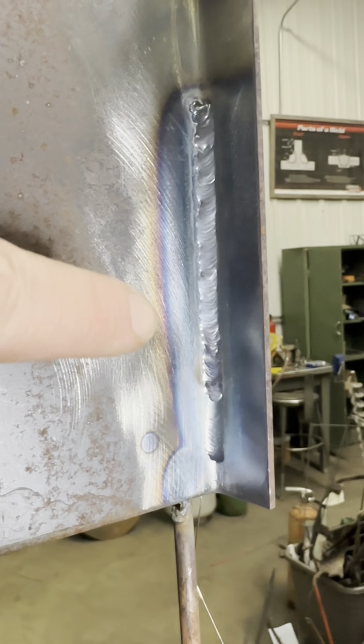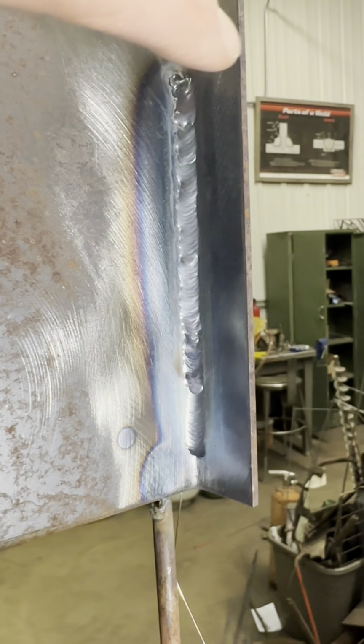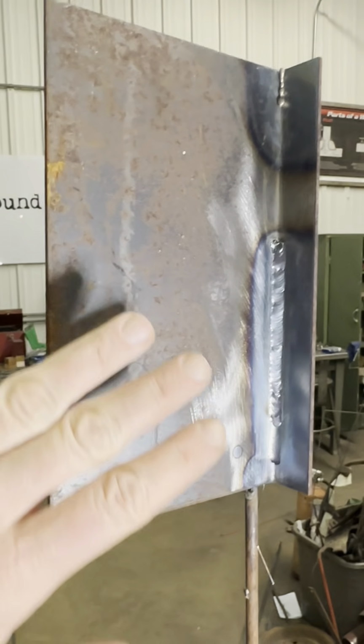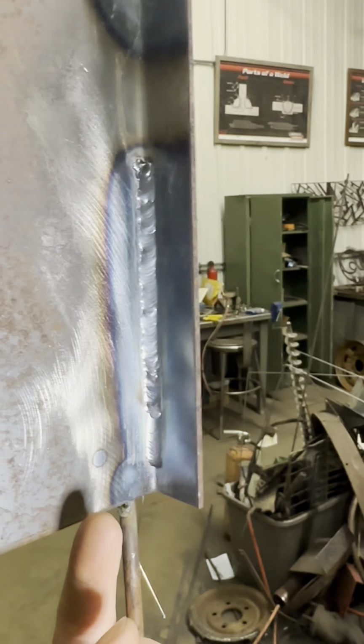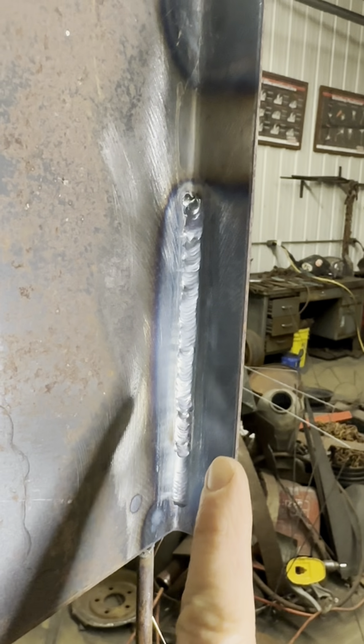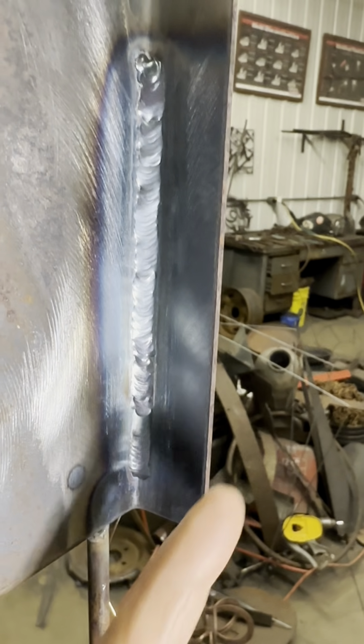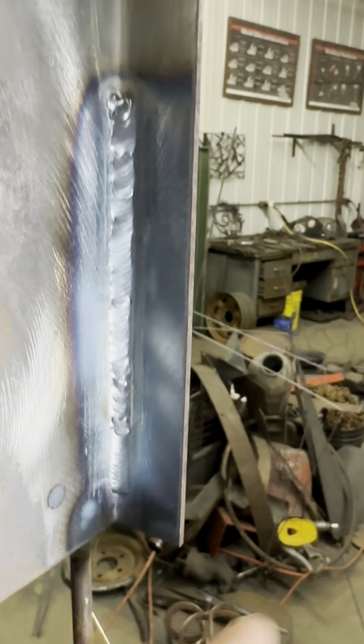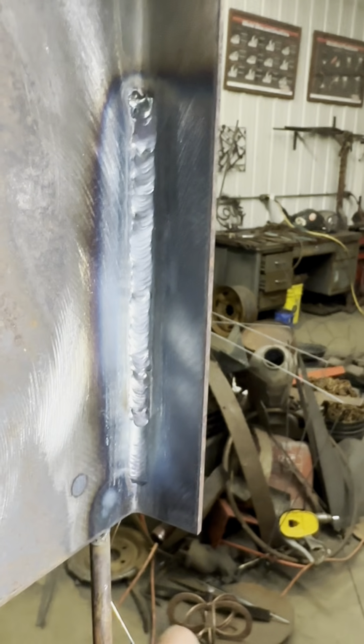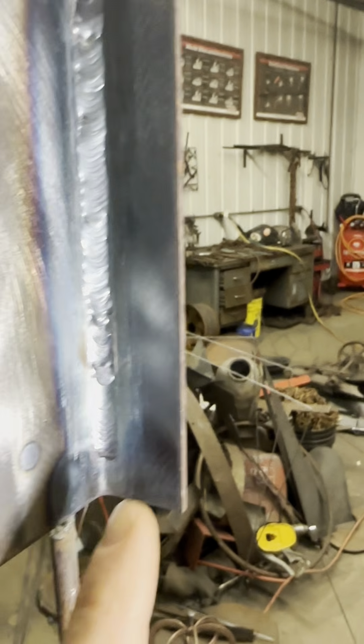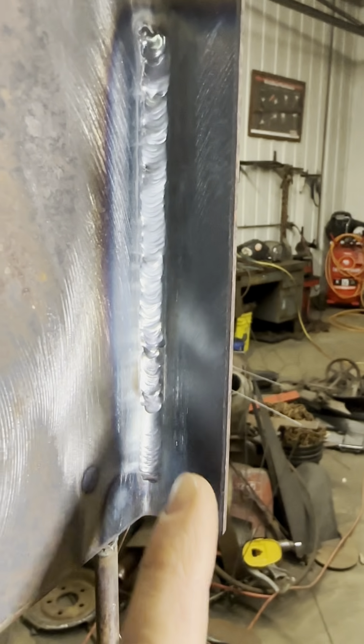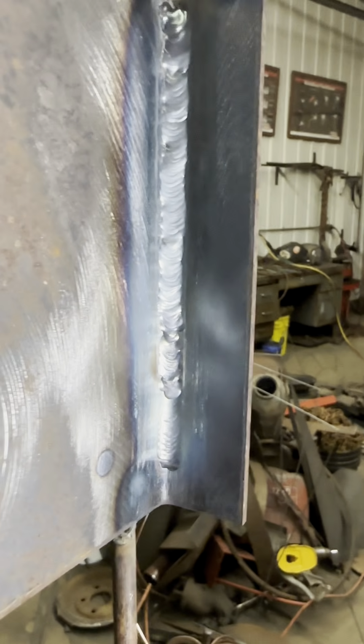By the way, this is a term I don't throw out very often. This is the HAZ, H-A-Z, the heat affected zone of the weld. And as you can see, because there's a lot more material here to act as a heat sink, the HAZ only goes so far out from the weld, but it consumes this entire webbing here that's only like a half inch big. The heat didn't have anywhere to go. It couldn't escape off the plate, so it just kind of built up and built up and built up. And that's not good for the material. The heat affected zone is where you see a lot of cracking and brittleness, and that's where corrosion will start.